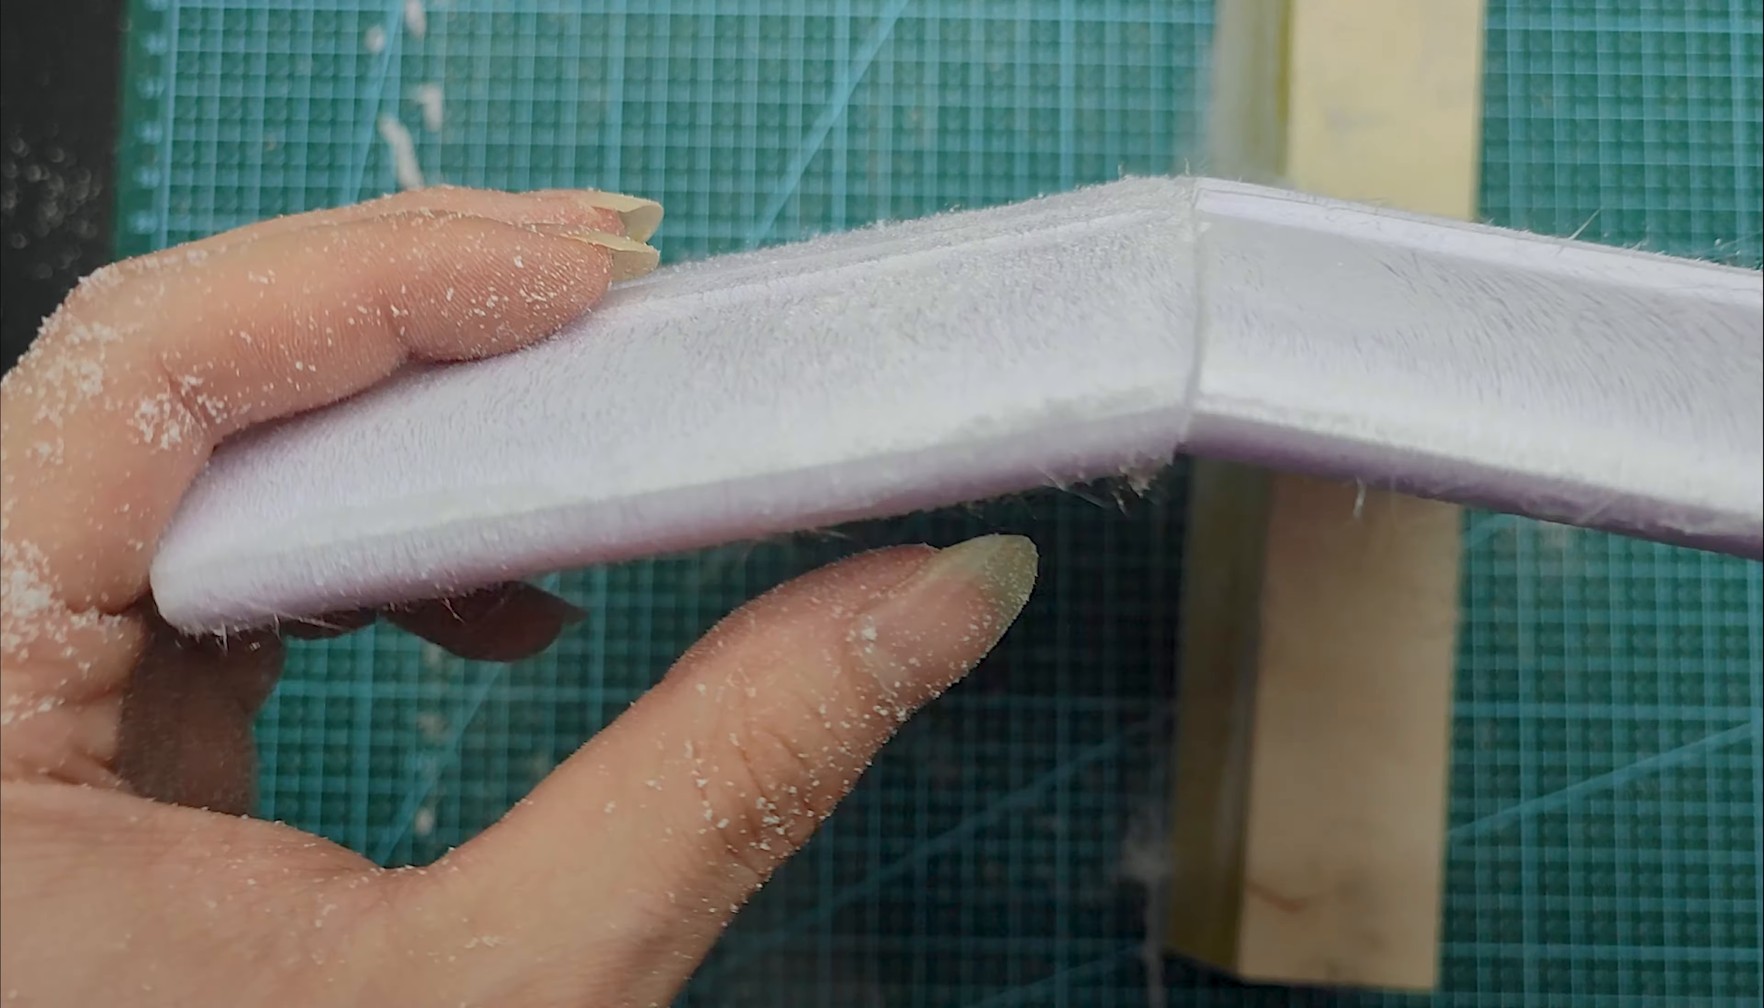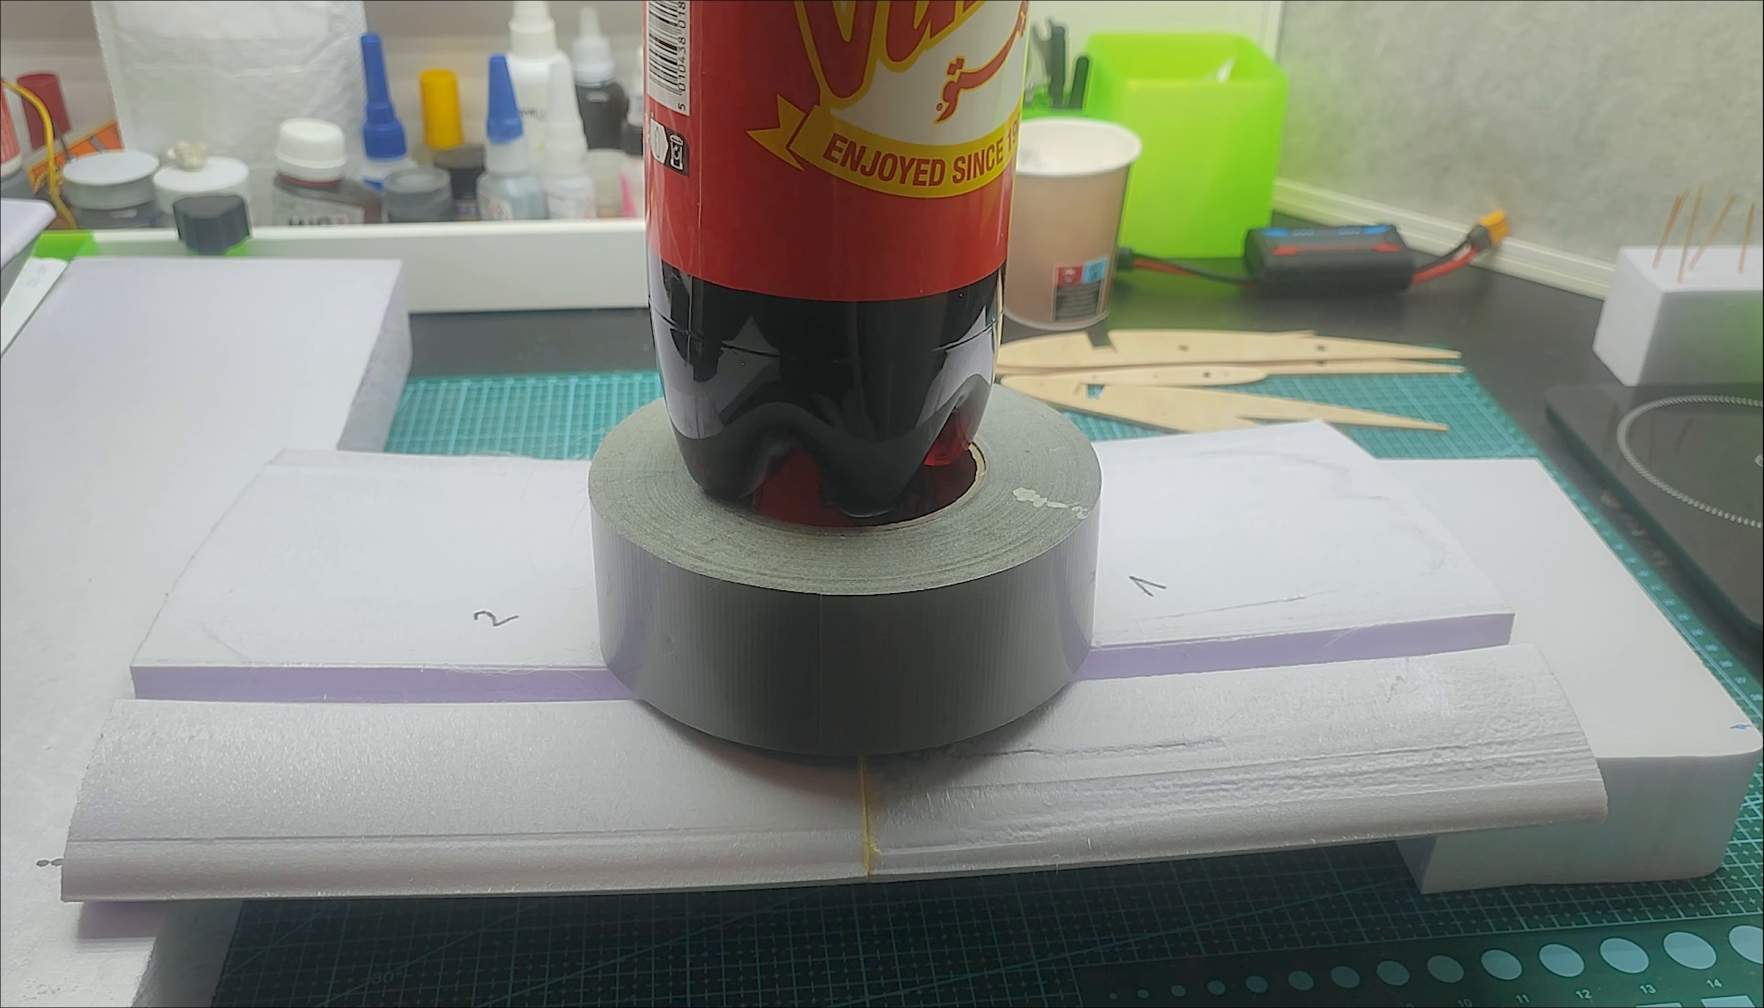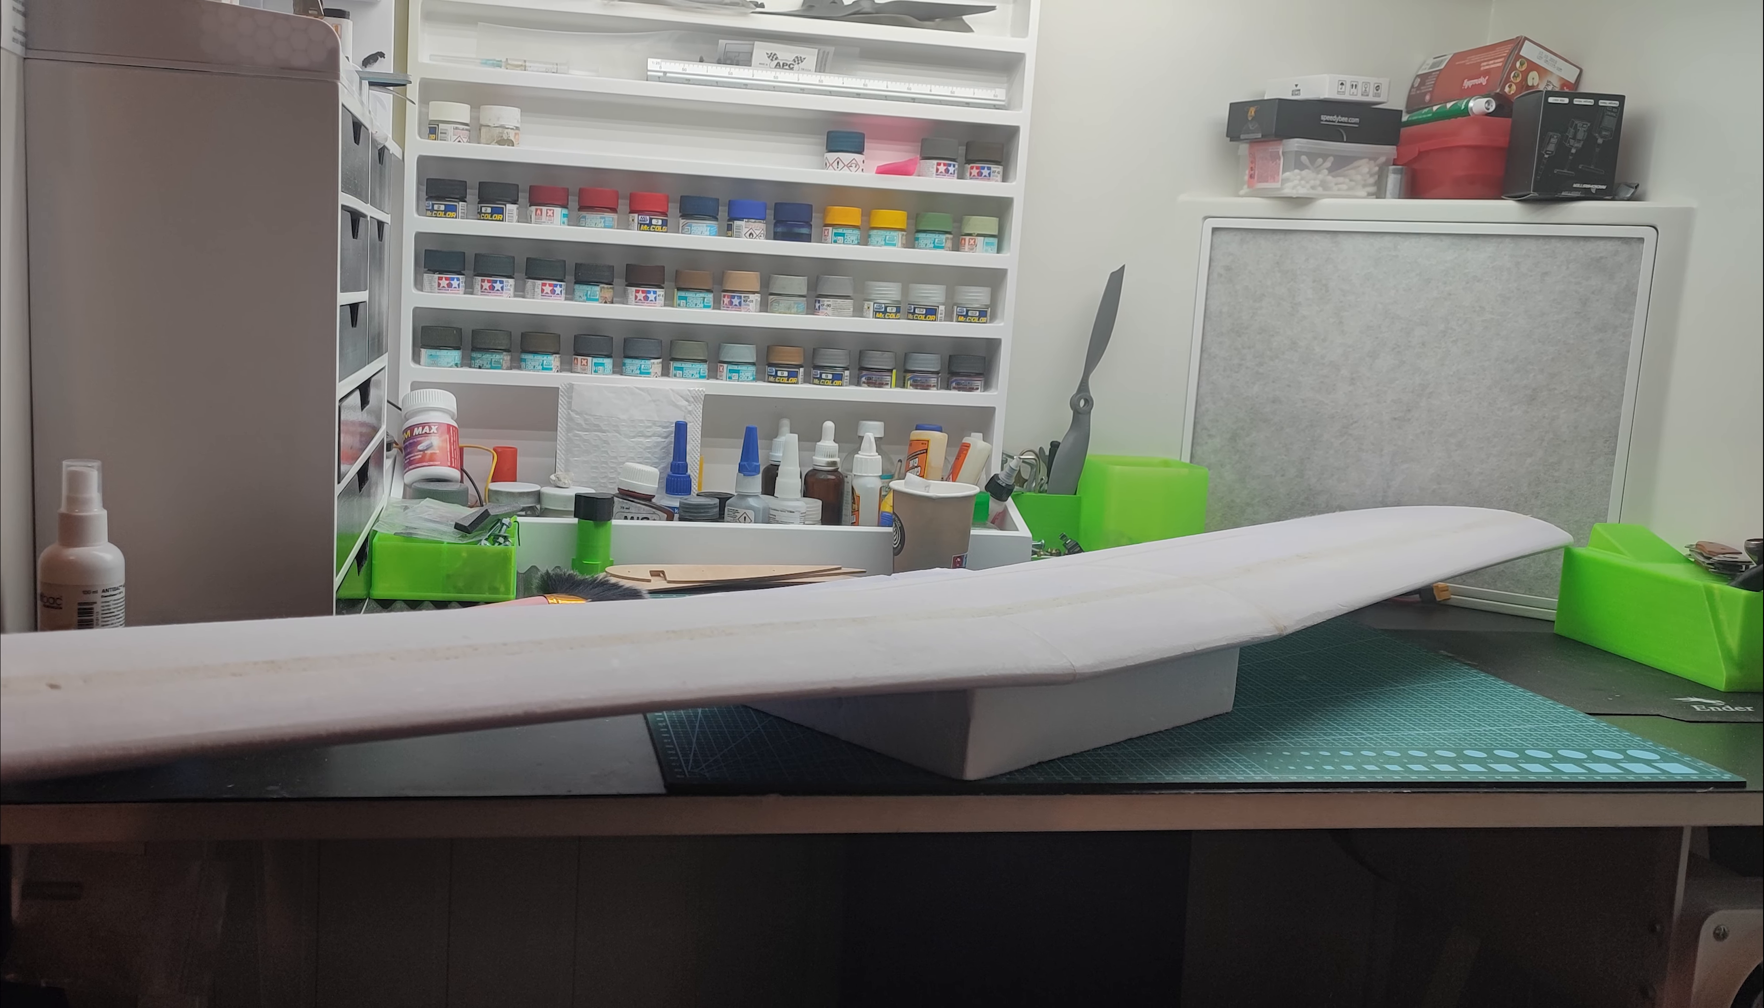It turned out Gorilla Glue will be a good choice. Here I forgot to poke some holes, which should make an even better bond. You can use a little bit of water on one face to help the reaction, especially if you are in a really dry environment. I was curious how well the glue will perform, so I glued my practice pieces together and next day it was time to test it. Very professional, static and dynamic test with 680g of duct tape and 2kg of beverage. Statically, it had no problem to hold both. Dynamically, also not a problem. So let's hit it even more. I dropped several times the duct tape from height of 60cm and the glue joint didn't care. And when it failed, it was by pressing the joint completely down. Most importantly, it was not the glue joint that failed, but the foam. So Gorilla Glue passed the test.